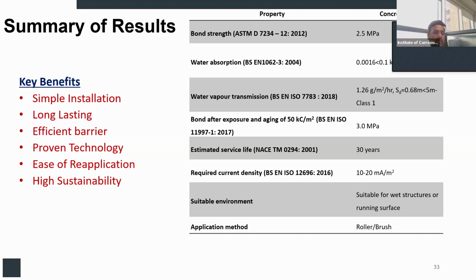Even after bond exposure and passing a charge of 50 kilocoulombs per meter square, the bond strength is still very high. Estimated service life, as tested per NACE standard, is about 30 years. It's within the required current densities. It's suitable for both wet structures and running surface, and can be easily applied by roller or brush.